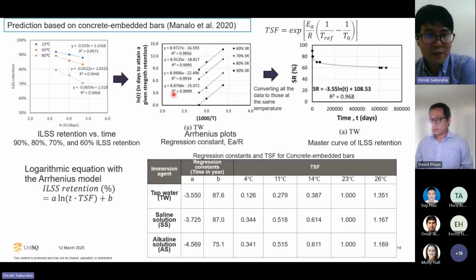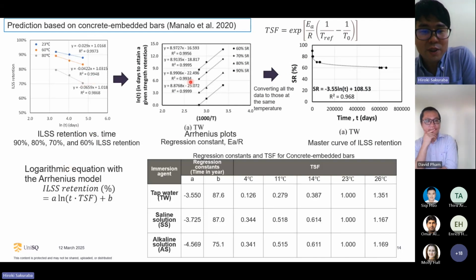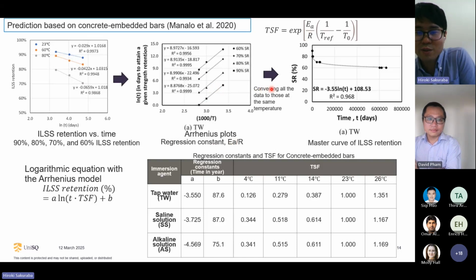And also, I briefly explain the prediction method based on the Arrhenius model. So first, we have ILSS retention versus time based on a logarithmic equation. Then we can have Arrhenius plots. So we can obtain the regression constant from this Arrhenius plot. Then based on this regression constant, we can convert all the data to those at the same temperature. So we can get this kind of master curve of ILSS retention. And also, since we have a time shift factor, we can calculate master curves corresponding to temperatures of 4 to 26 degrees Celsius. These correspond to the results of field durability.